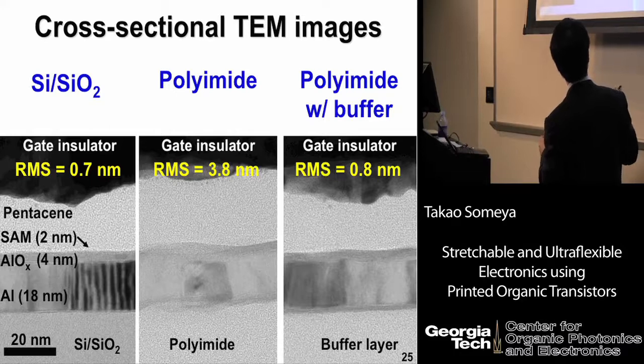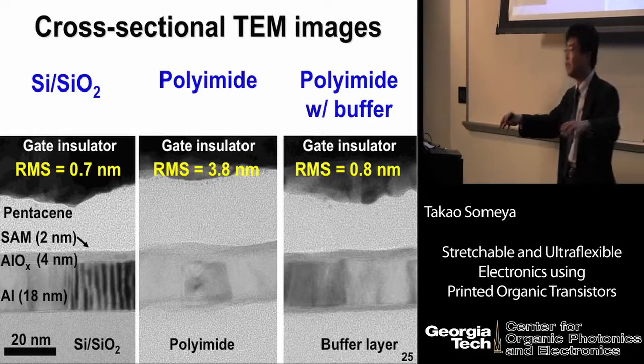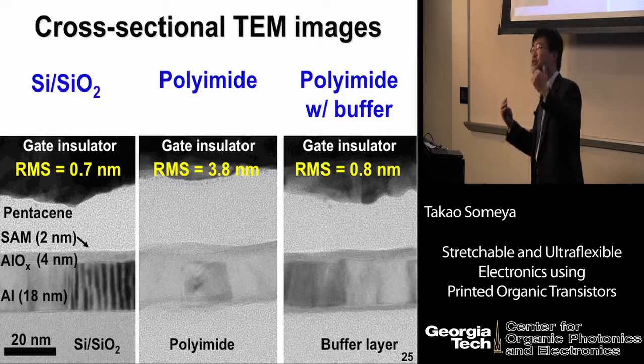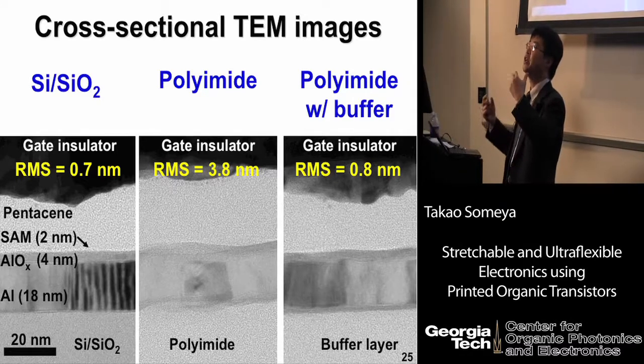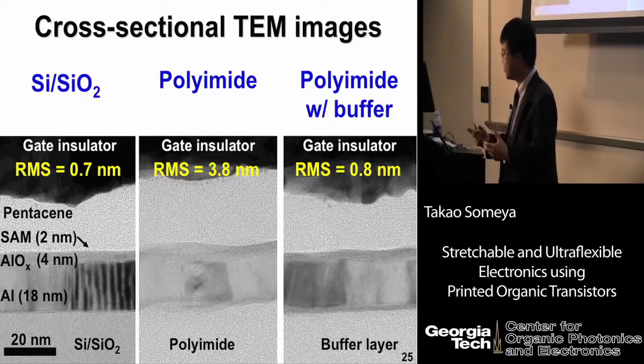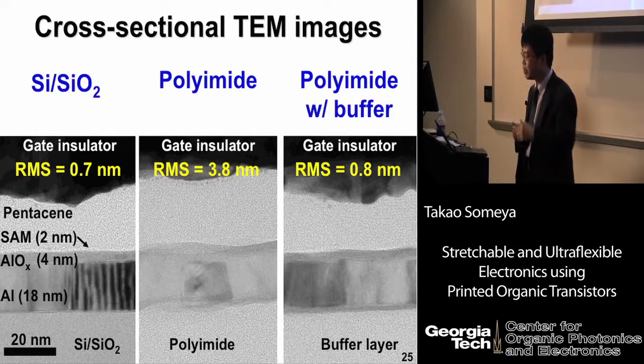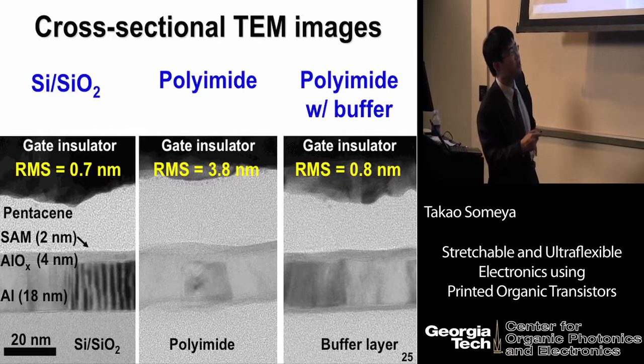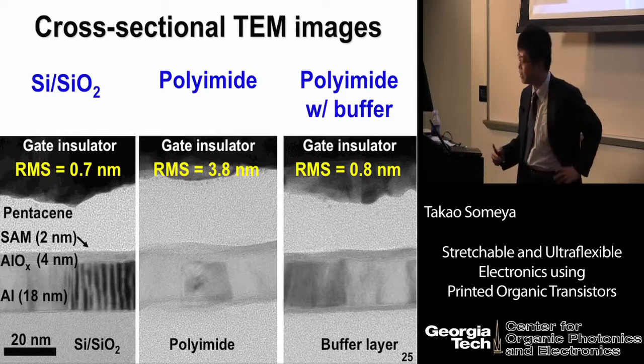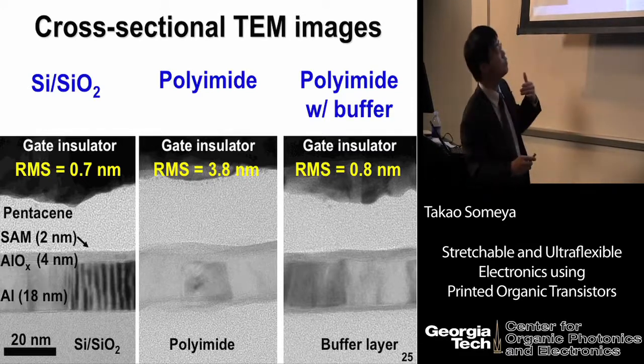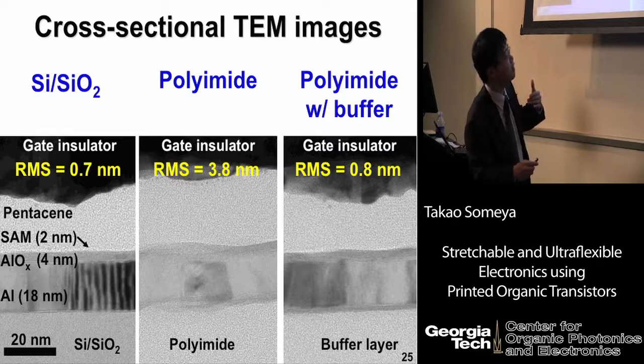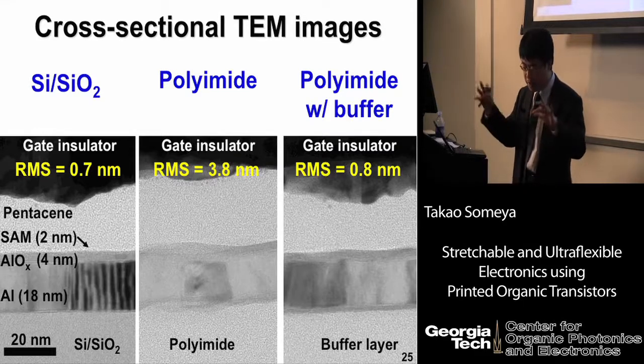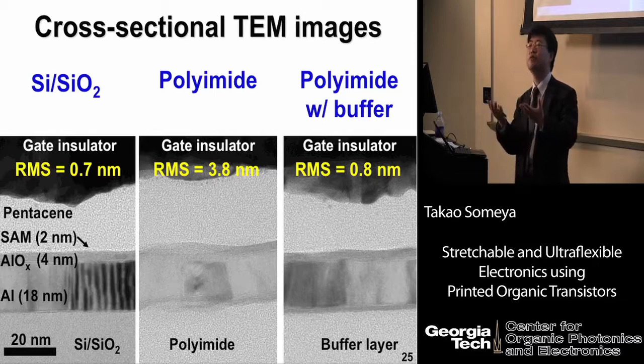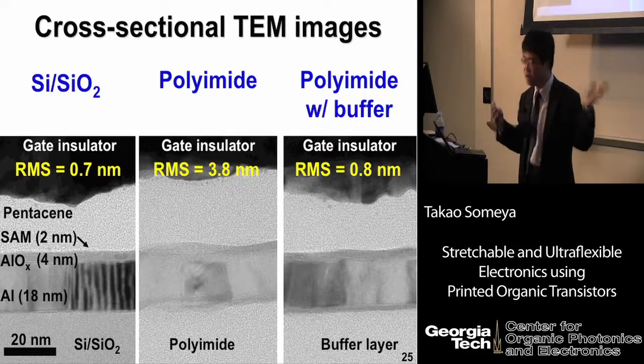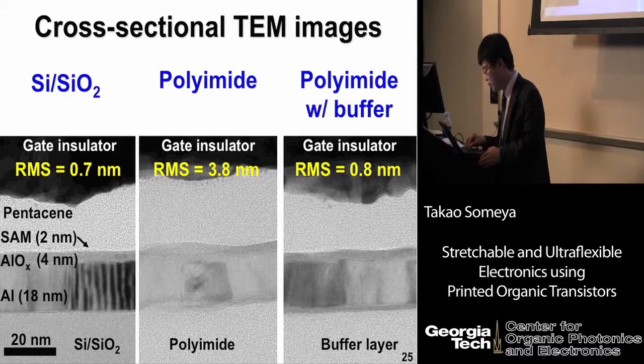As you can see, the surface of plastic film is quite rough, so we cannot form a nice self-assembled monolayer without causing pinholes. To avoid that problem, we deposit a quite good surface planarization layer using polyimide precursors, and then we achieve almost equivalent surface smoothness. On such a smooth surface, we can nicely form the self-assembled monolayer. So this was one of the most important contributions in our group.